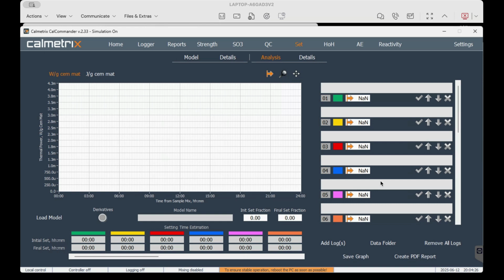The rule of thumb that I typically show people how to use, because it's the simplest, is a great tool for comparing sample A to sample B, and it's applicable to both the semi-adiabatic and the isothermal. In both cases, you also have the option of creating an empirical model where you take a standard mix design, run the calorimetry, do physical set time testing, and then correlate and create a model that gives you the fractions based on empirical modeling. So that's the other option, besides the 1/3, 2/3, or the 0.21, 0.42. Those are different rules of thumb that various folks in the industry use.